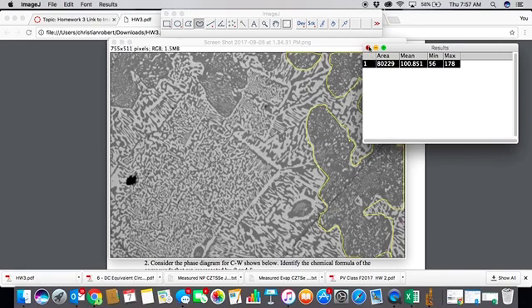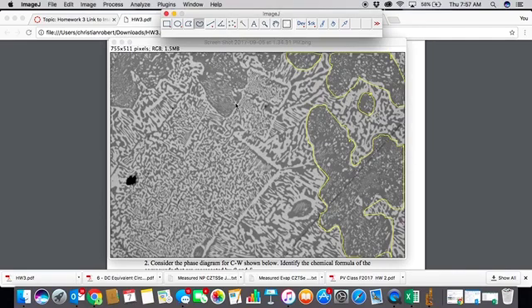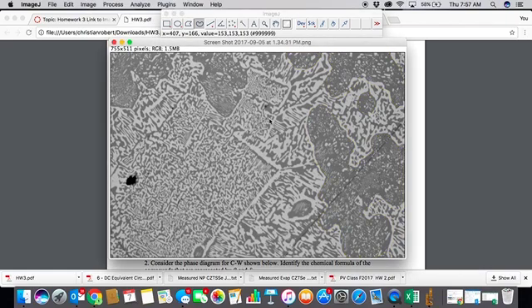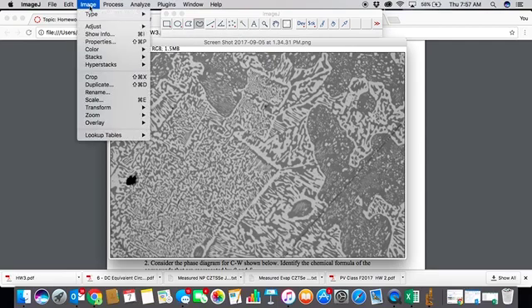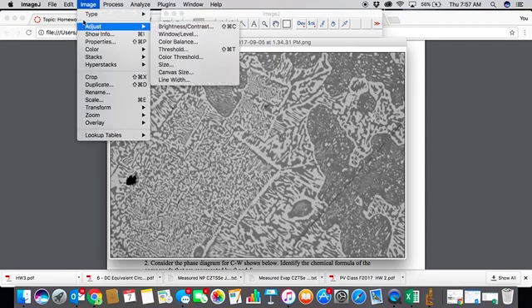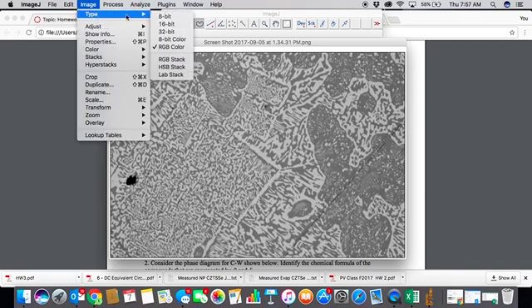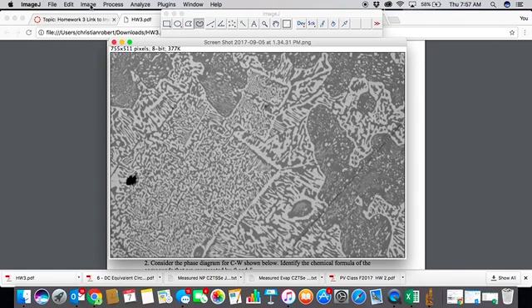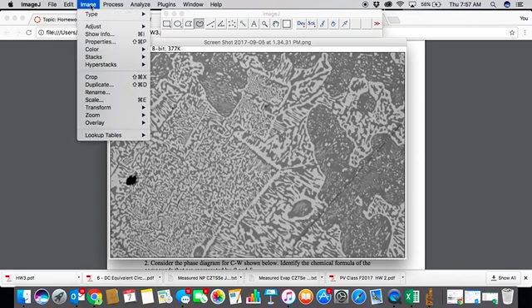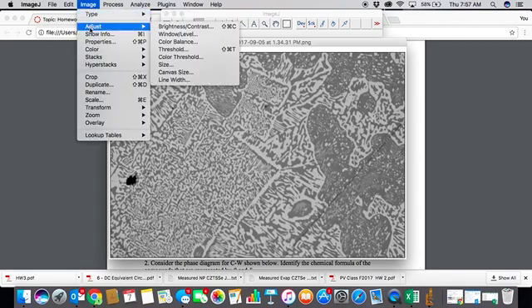It's a little bit more versatile, I think. I'm going to make solutions for both methods. So you want to deselect everything. You can do that just by clicking anywhere. And if you go to this image, first you'll need to change it to 8-bit. That just makes it black and white. It already was black and white, but since you took a screenshot, it thinks that there's colors in it. So after you change the type, you can go to adjust and then threshold.